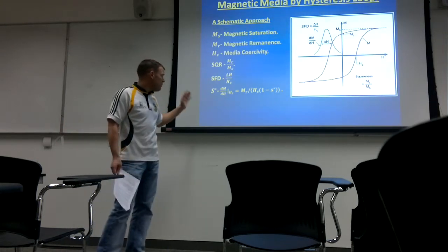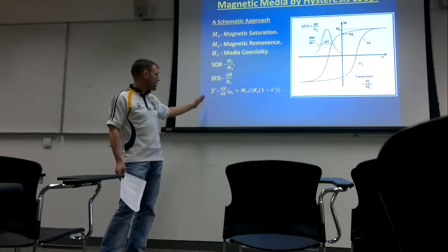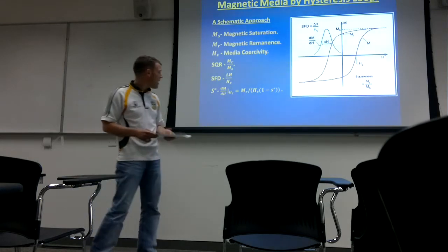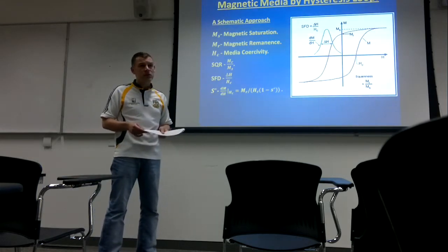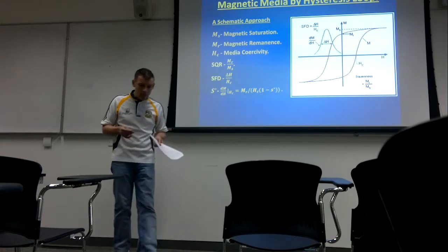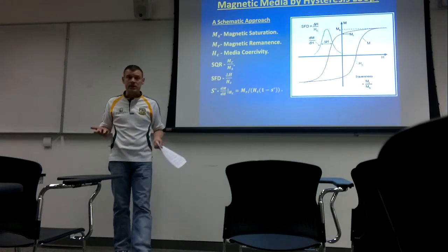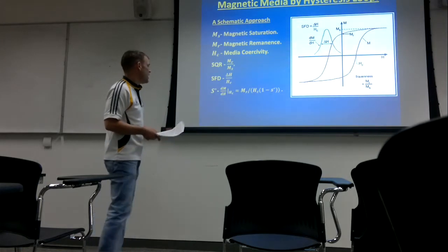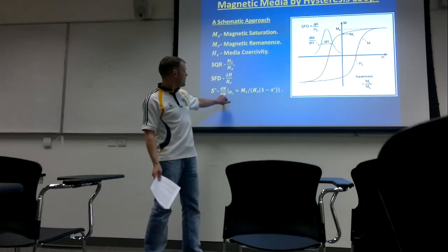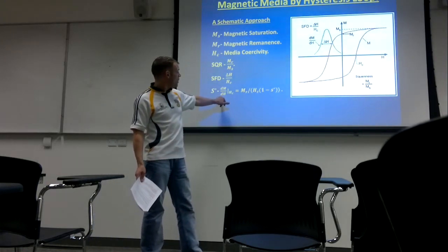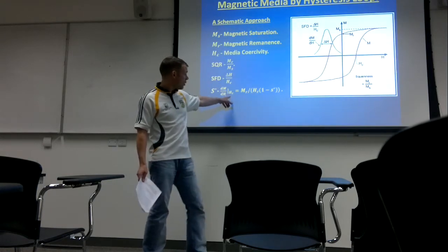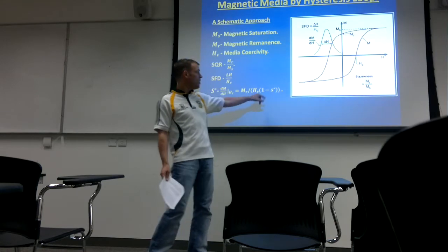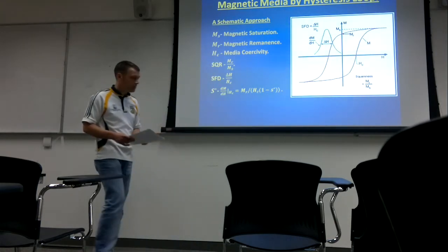Another parameter related to the slope at the point of coercivity is S star. It's used in calculating maximal output signals for read processes. It's found by the derivative, the slope of the curve at the coercivity point, which equals remanence over the coercivity by 1 minus S star.